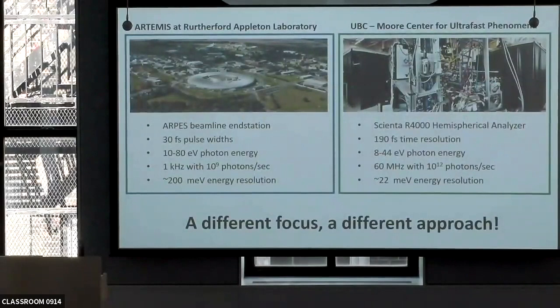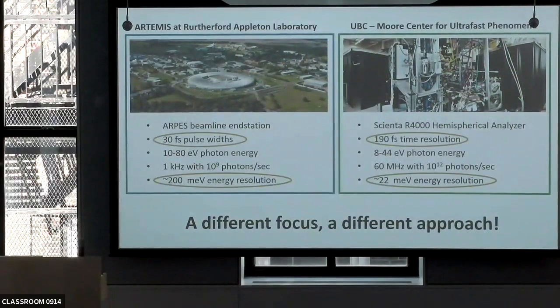Before, I said there are some large-scale facilities where you can do this kind of work, but what are the parameters? So this is our chamber in UBC, where you have an emission chamber and 2 lasers with 6 eV and up to 40 eV. Here is Artemis at the Rutherford lab, and here are the features you should look at. They can generate an amazing temporal resolution, 30 femtosecond, but then you look at energy resolution and usually it's 200 meV or above, so often many hundreds of meV. In our case, 190 is what we have in this particular experiment, but 22 is what we can get. So it's an order of magnitude better there. And so really for this experiment, that particular machine wouldn't work.